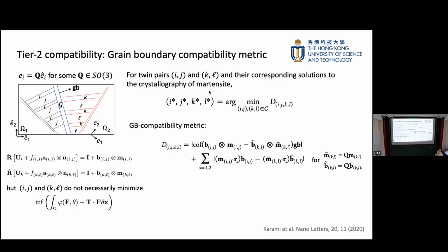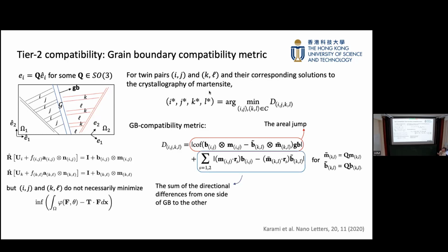It's just by observation. So we think, okay, if you have some grain boundary, we first want to probably minimize the area jump. That is the cofactor of the difference of the deformation from both sides. And then if you have two orthogonal in-plane vectors, we want to minimize the extension from the left side to the right side. That is this. Okay. So we just very, very naively designed this. And then among all compatible twin laminates, we just find the minimum values of this, corresponding to what twin laminates on the right-hand side and what twin laminates on the other side.